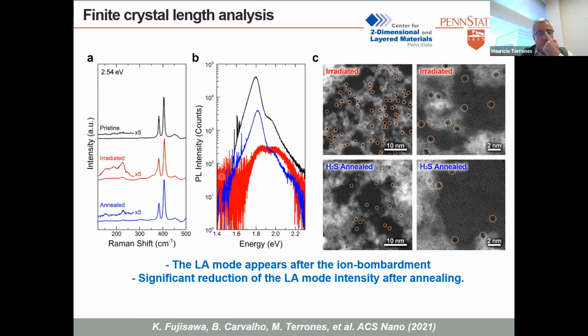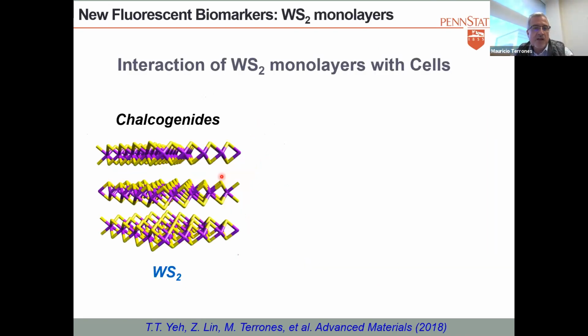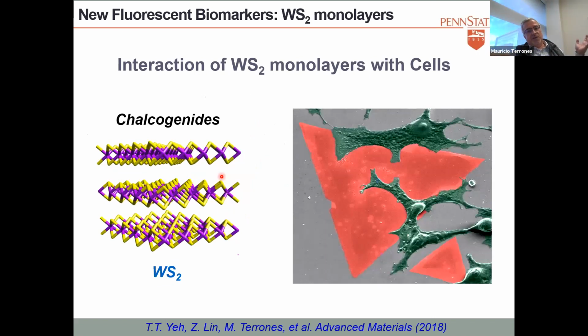We have a similar formula for molybdenum disulfide, but again, this is a way to use Raman spectroscopy and get an idea of how defective the samples can be. Let me just show you the work that we have been doing with bio and cells. You know that the monolayers fluoresce, right? And this is a cell. So can you get these cells to ingest this material that fluoresces, and can you use it as a contrast agent for imaging cells? And this is something that we did.